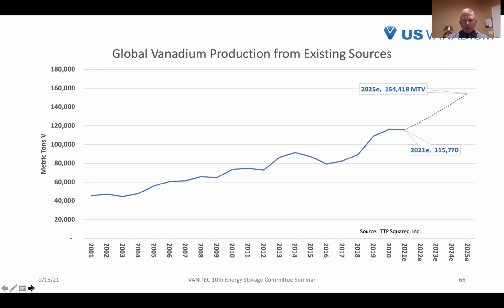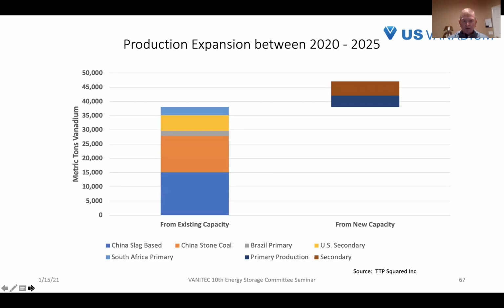Next, please. This is a line that shows a historical trend in terms of vanadium production. You see a fairly steady climb from 2001 up through 2021. Our forecasts looking forward are that we expect to see relatively strong growth in demand for vanadium. And as a result, we expect to see the supply of vanadium growing. So we're showing here an increase in supply from about 116,000 metric tons of pure vanadium in 2021 up to 154,000 metric tons of vanadium in 2025. And the next slide will show us how we suggest we're getting there.